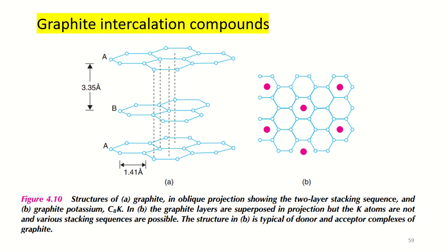Potassium ions look like they are sandwiched between pairs of carbon rings, giving the potassium ion a coordination number of 12. If all such sites were occupied, the stoichiometry C2M would result, but in C8K only one quarter are occupied in an ordered fashion.